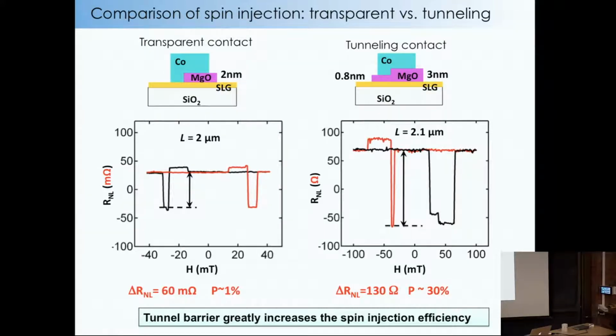In clean room processing, it's standard, but typically it's pretty thick. If you try to put gold on a device, it'll peel off because it doesn't react. So we knew that titanium was a favorite one, and we didn't want to use things like chromium, which also get used, because that's magnetic. We wanted something that's non-magnetic and sticks.